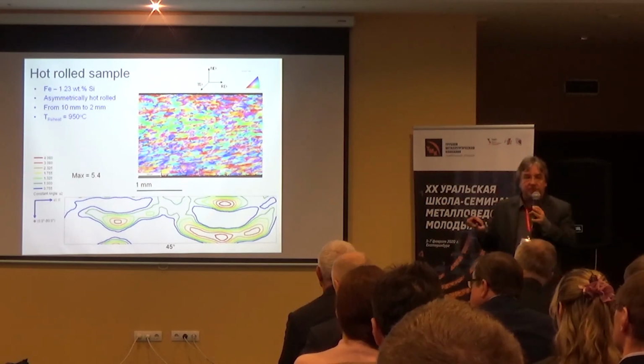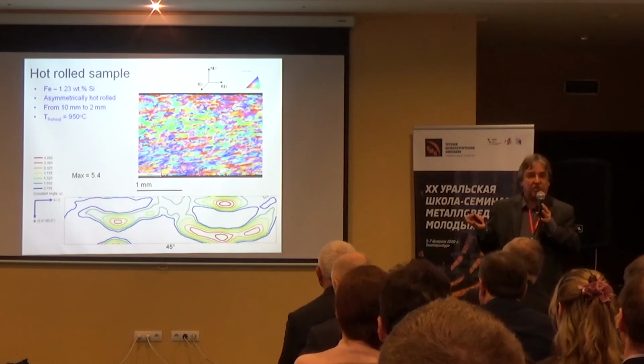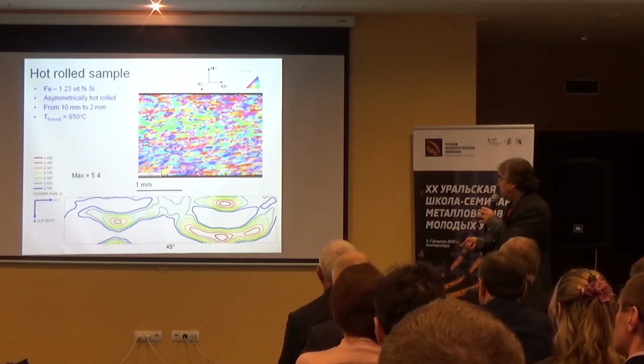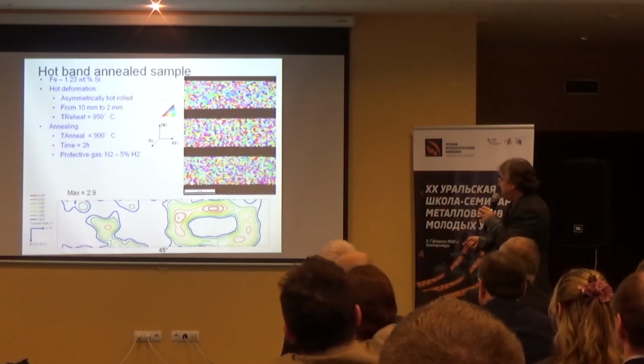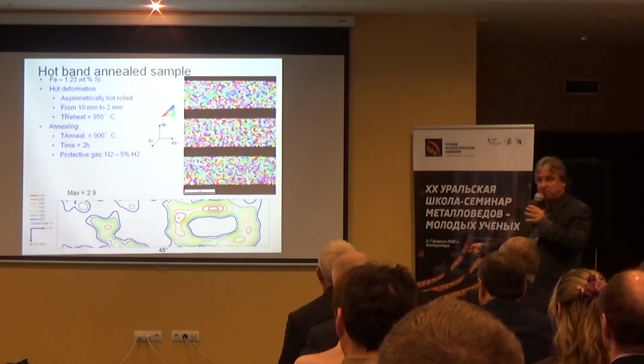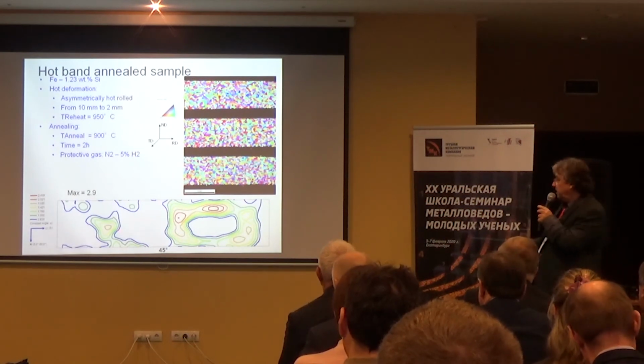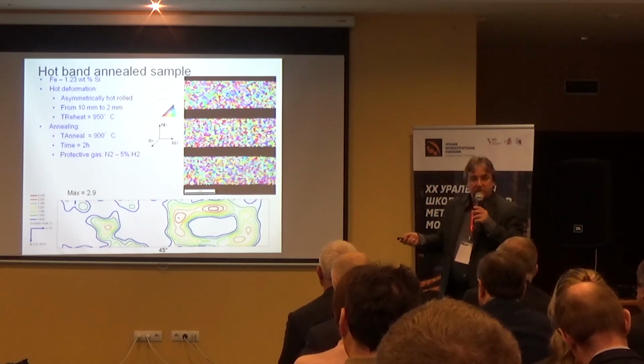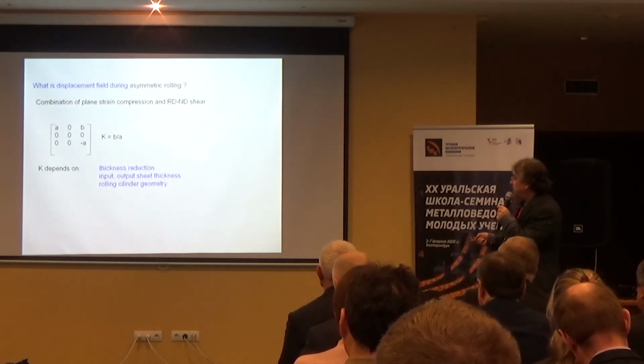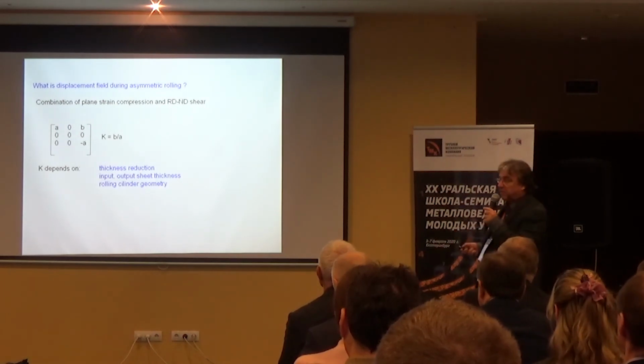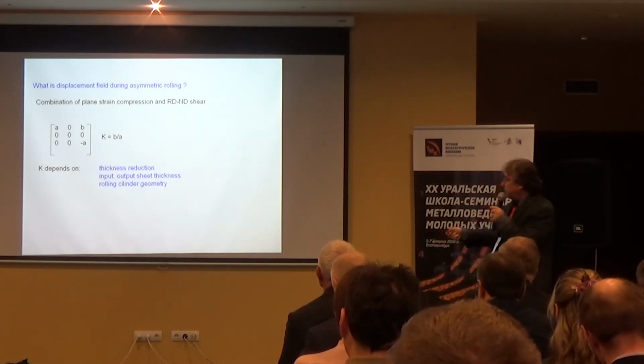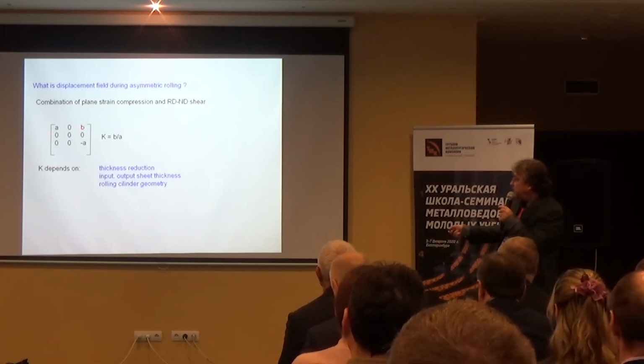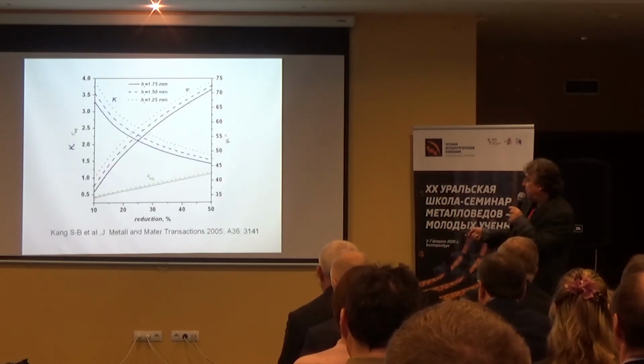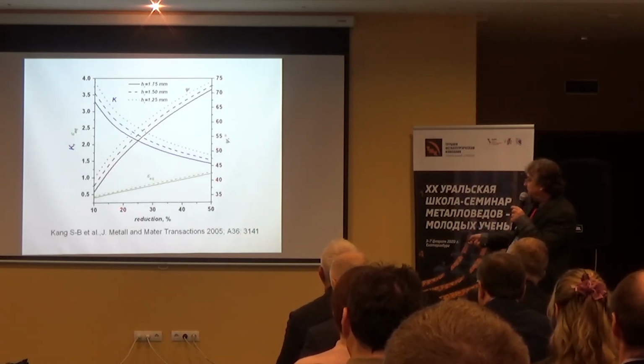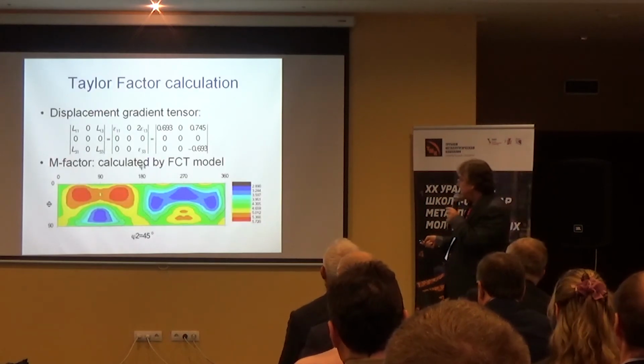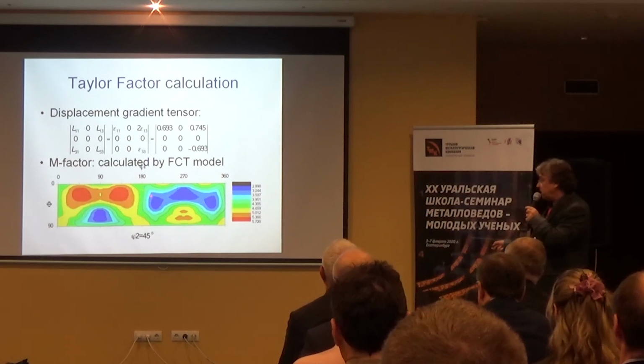You see, this is very much different from our typical alpha-gamma fiber texture from plane strain compression. So I'm not going to explain this. What is interesting to see is that also this is the recrystallization texture. This is the texture after recrystallization, and it looks a little bit exotic. So we're not very familiar with this. But now we have a different type of displacement field, a different type of strain tensor, because we have a shear component now, which was not there before. Based on a paper, we calculated the strain tensor, and now this is our Taylor factor map. You see, it looks totally different.